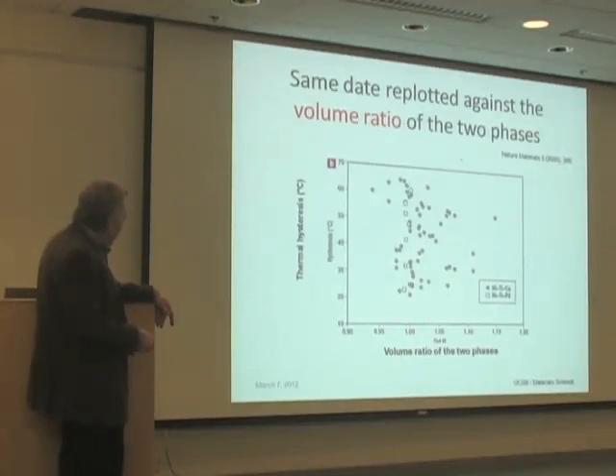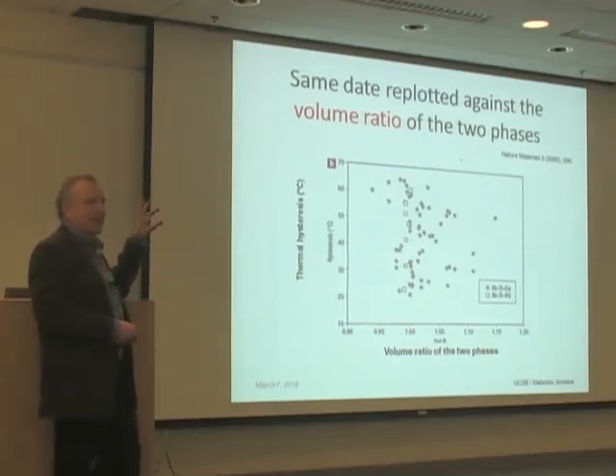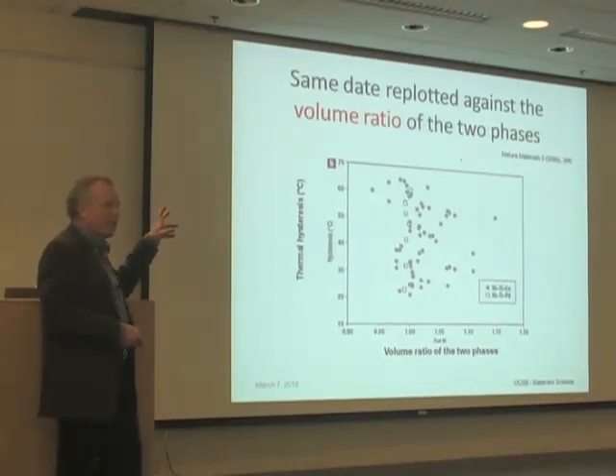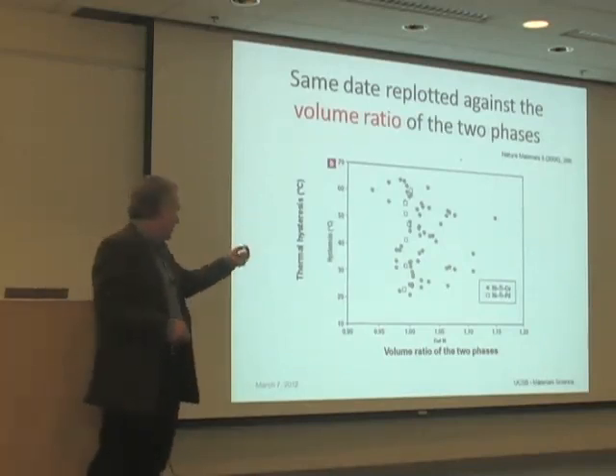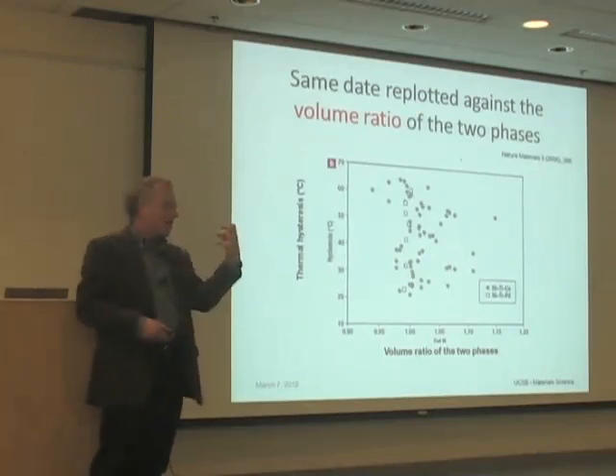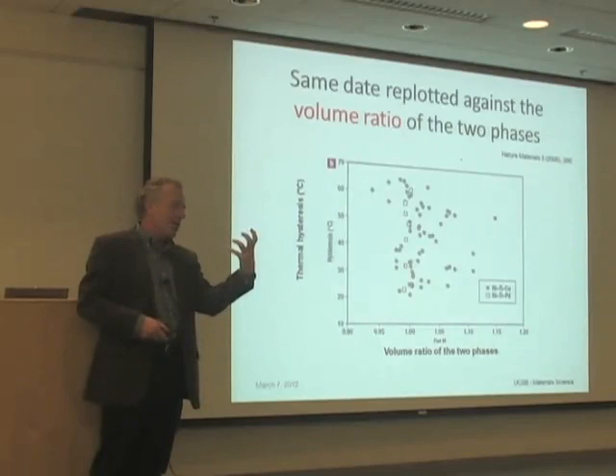Okay, so this is the hysteresis being plotted here. So I'm replotting the data, but now versus the volume ratio of the two phases. So of course, if there was anything that had to do with lattice parameters that should affect hysteresis, people would believe it would be the volume change, just like I discussed earlier. Because of course, when this is not 1, it means the new phase is growing up in a hole of the wrong volume. So there has to be a lot of stress there, right?